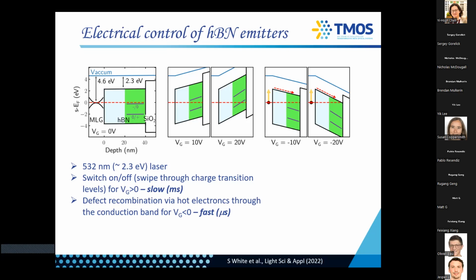You would have hot electrons going to the conduction band of hBN, and under very strong bias, they would propagate and recombine always at that defect. Now, this theory is very easy to check because you can change the excitation wavelength. Remember, we excite with a green laser, so it's about 2.3 eV, going from this Fermi level to the conduction band here. If we now change the laser to, let's say, red, much lower energy, then you should not see anything. And that's indeed what's happening.